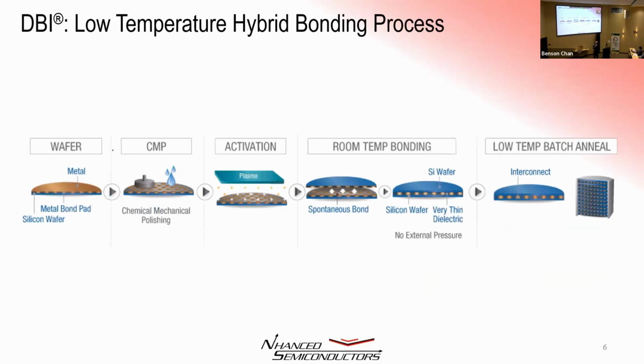So how do we do this little miracle? DBI is the trade name that Xperi uses, direct bonded interconnect. It actually is pretty straightforward. In our fab, for the most part, the first thing we do is add a layer of copper or nickel interconnect on top of the wafers. We polish it atomically smooth with CMP, do an activation. It can be chemical or plasma. And then at room temperature, you can bring the wafers into contact and they instantaneously bond.